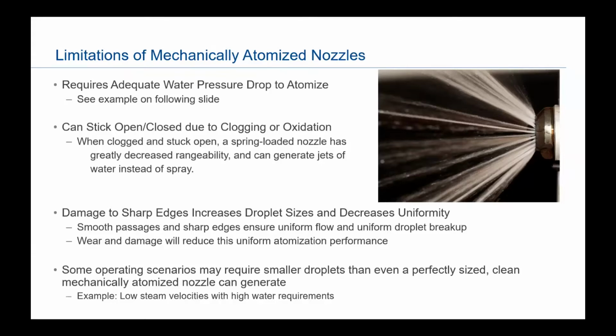Then over time, any damage to the sharp edges at the exits of the nozzle can increase your droplet sizes and decrease uniformity just as they wear over time. And so that will reduce the atomization performance, which is why we generally recommend inspection and replacement of the nozzles on certain intervals just to maintain optimal performance. But as Eugene was saying, we're starting to find operating scenarios that may also require smaller droplets than even a clean, correctly sized nozzle can generate. Particularly these operations with low steam flows and high water requirements that he was describing.